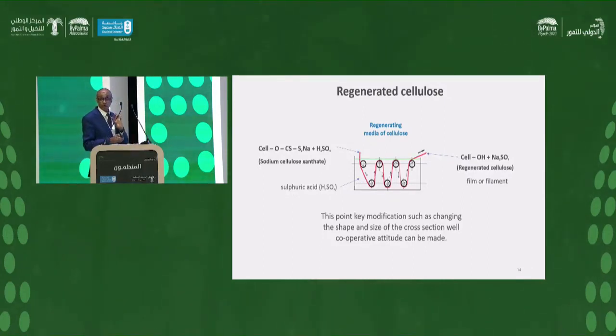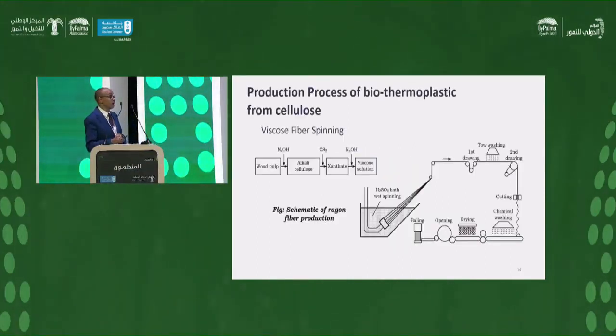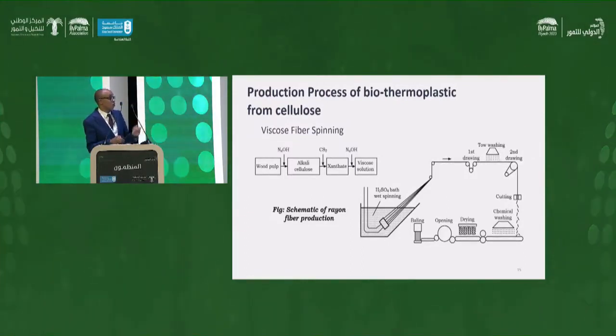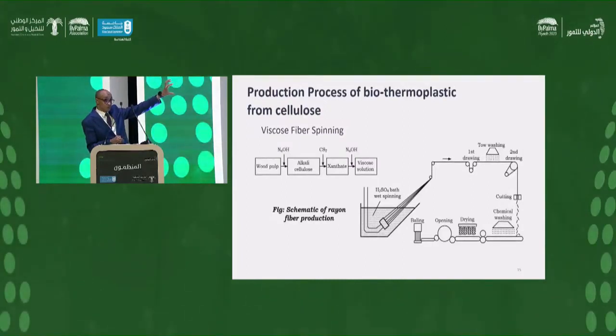And the main point is the viscosity and the rheological behavior of the material. This is the process which is actually used to produce thin rayon from cellulose. Exactly, we have the same approach to obtain the viscous solution. The difference is that in the case of rayon, we have more specific surface of the treatment, and the time of the treatment is very short. In the case of the film, we must have a thin film, and the duration of the treatment is very large.